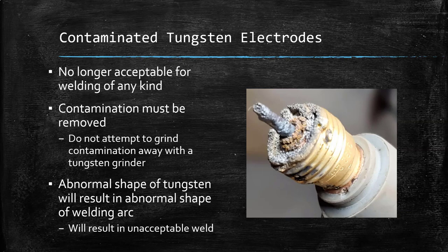If you're using the pedestal grinders or tungsten grinders that are specifically for tungsten electrodes, and you stick a contaminated tungsten in there and use it, you've basically contaminated that entire grinding disc, that diamond disc. So the next person who uses the grinder after you is going to contaminate their tungsten, and every person after. So remove the contamination completely before you stick your tungsten back into a grinder and resharpen it.